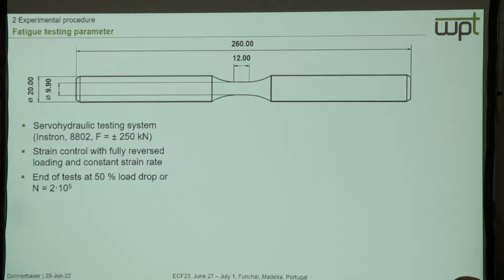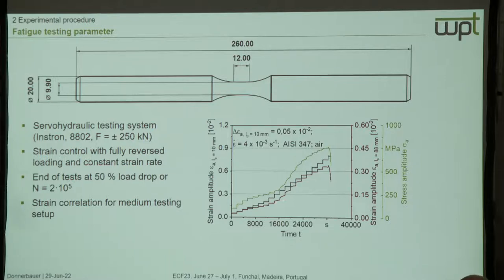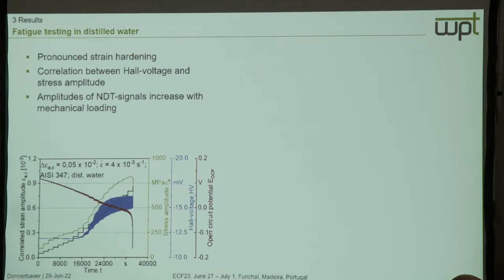End of tests was at 200,000 cycles, so we are looking at low-cycle fatigue behavior, or at 50 percent load drop. A test result from the medium testing setup shows that above a strain amplitude of 0.3 percent the stress amplitude starts to increase sharply — this is the pronounced strain hardening behavior which is quite well known. Four of these tests were done: two with the 10 mm gauge length and two with the 88 mm gauge length, and the measured strains were correlated to enable testing in medium.